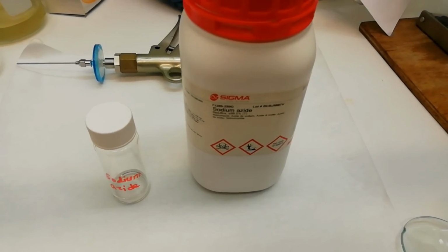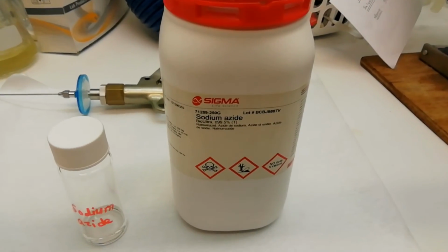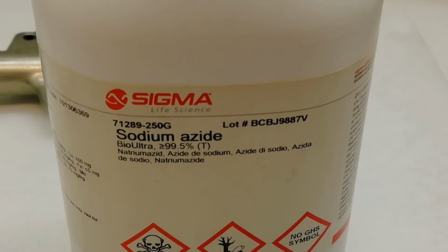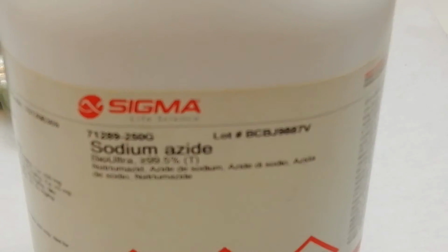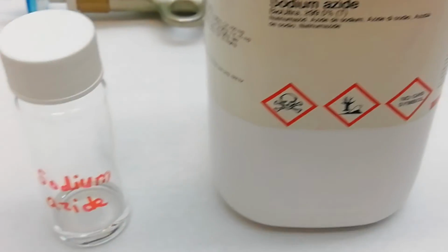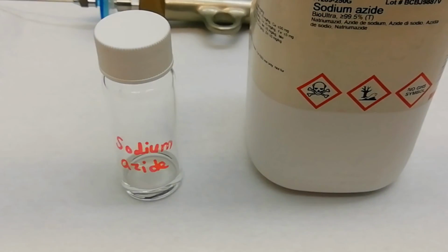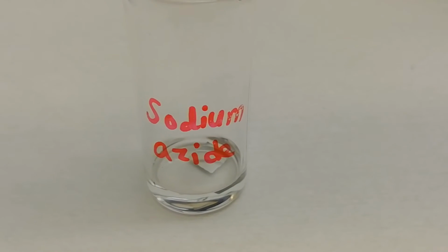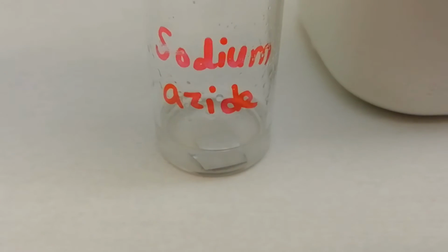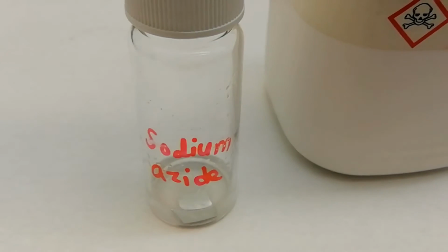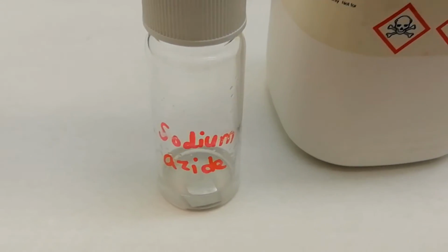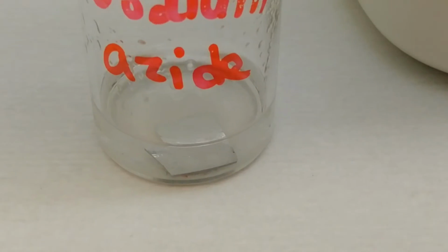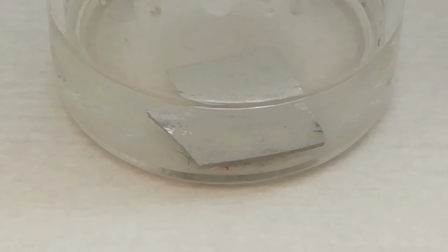Functionalization of this bromo-terminated phosphonate modified aluminum oxide surface. The surface was further reacted with sodium azide to form the azide group for the additional click reaction. To obtain the azide-terminated aluminum oxide surface, the substrate was immersed in a 0.1 molar sodium azide solution in dry DMF for 16 hours at 60 degrees Celsius under nitrogen or argon in a closed glass vial.